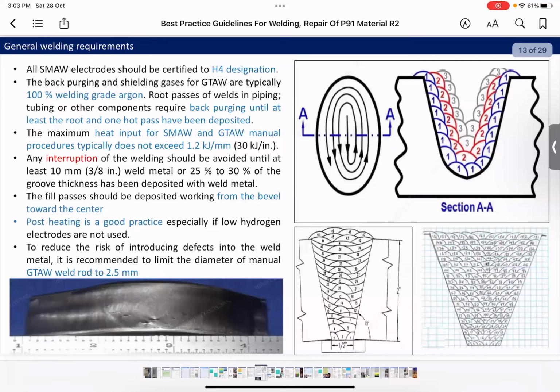General welding requirements here, as I said, all SMAW electrodes should be certified to H4 designation. The back purging of the shielded gas for GTAW is 100% welding grade argon. And the back purging shall be kept until at least the root pass and one hot pass have been deposited. So the maximum heat input also should be 1.2 kJ. This is why we restrict using small filler wire of 2.5 or 3.2 mm to the root, to reduce the heat input and reduce the width and the extent of the heat affected zone inside the base metal.